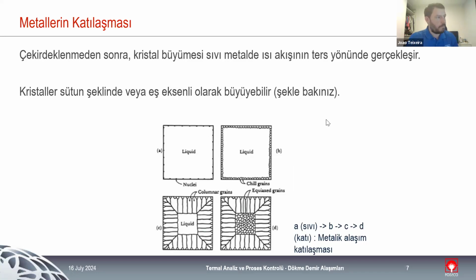And this is basically the scheme of how solidification happens in the liquid melt. If you don't give anything to the liquid metal, the solidification happens from where it is colder to where it is hotter. So when we pour the liquid metal into a sand mold, a green sand mold, for example, the solidification happens from the boundaries of the sand mold to the center. So it's one direction only. Only at the end, and you can see here in the image, we have what is called equiaxed grain size, grain boundaries. So they are not one directional. They are nucleating randomly in the melt. The main objective with the inoculation step is to have this type of nucleation happen at random spots inside the mold and not have a one direction solidification of the cast.